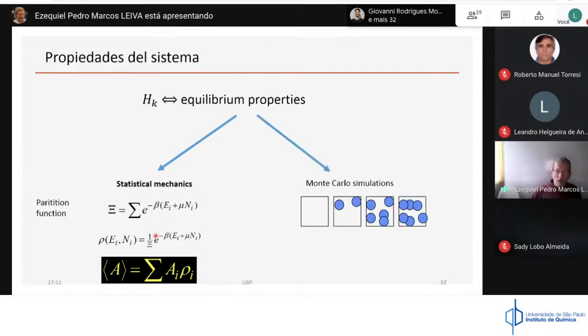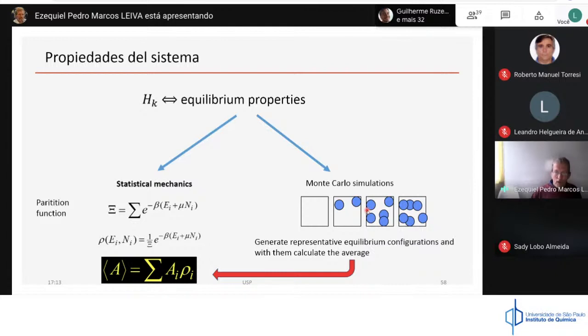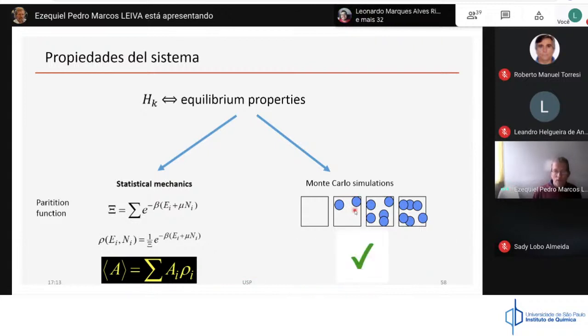The other way is by Monte Carlo simulation. Monte Carlo simulations are just a way of generating different structures, and from these structures you generate averages. The structures that you generate are representative of equilibrium, so you can calculate average properties, not through statistical mechanics, but just by running a number of configurations of the system. This is in some sense similar to molecular dynamics in that you get configurations, and from these configurations you get properties, but it is different in that these are equilibrium properties. You have no dynamic information in this Monte Carlo simulation.